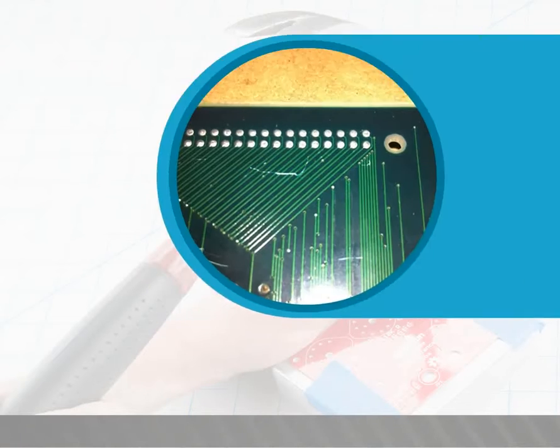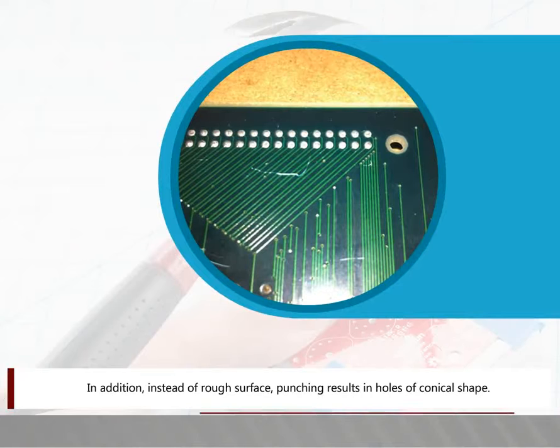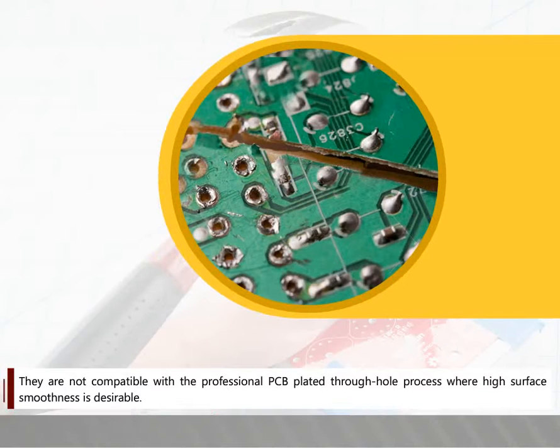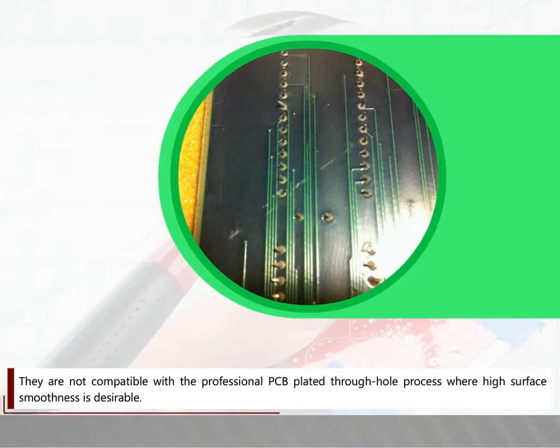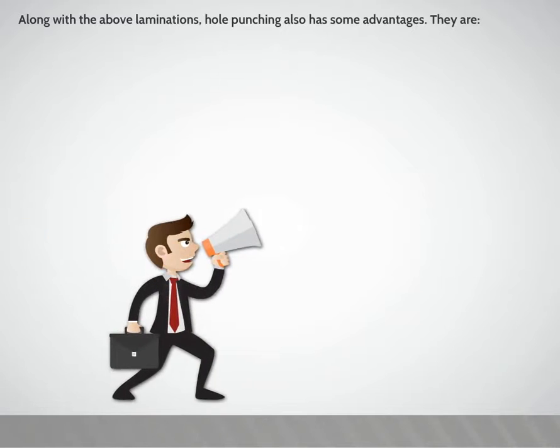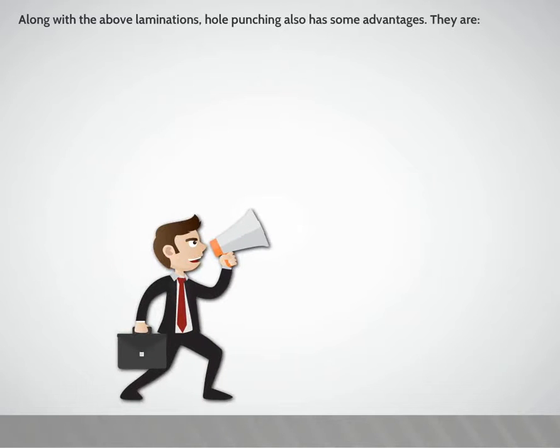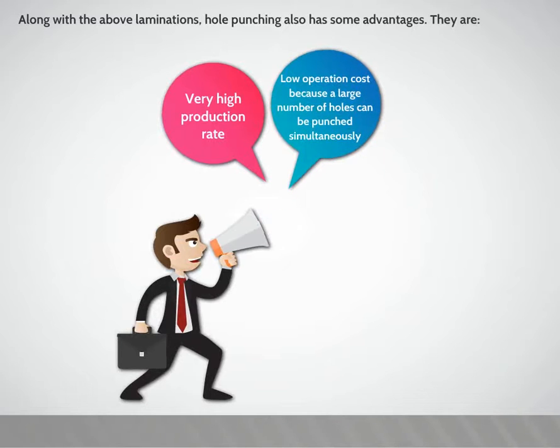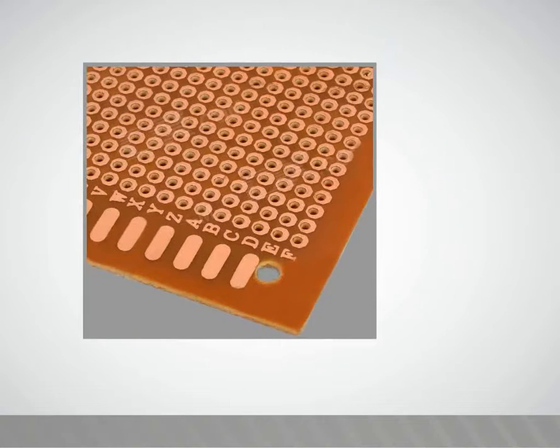Punching of holes. The other disadvantage of punching is the pad delamination and laminate cracks on adjacent holes. In addition, instead of a rough surface, punching results in holes of conical shape. They are not compatible with the professional PCB plated through hole process, where high surface smoothness is desirable. Along with the above limitations, hole punching also has some advantages. They are very high production rate and low operation cost, because a large number of holes can be punched simultaneously, and high accuracy and repeatability of the hole position.